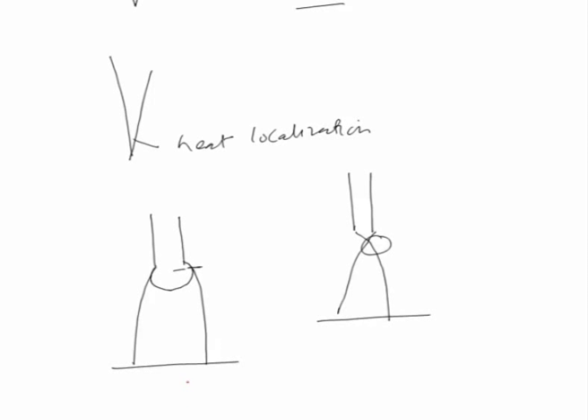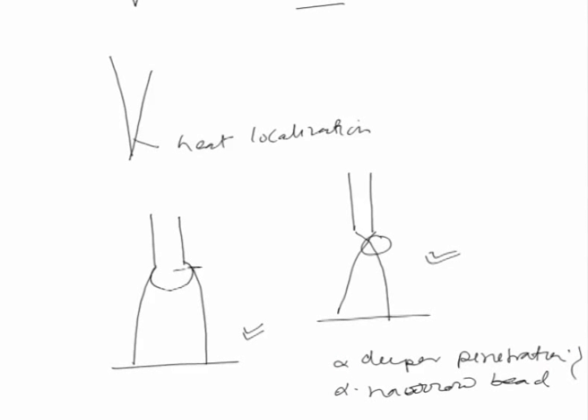So, as far as the heat localization is concerned, it will be less in case of the ball shaped, while it will be more in case of the very pointed conical shaped tips. And therefore, ball shaped tipped electrodes offer a longer life than the conical shaped tips with very small angles. But the conical shaped tipped electrodes offer deeper penetration and a narrow weld bead is obtained. So, because of these advantages, as per the situation, we can work with either the pointed conical shaped electrode tip or the ball shaped tip.